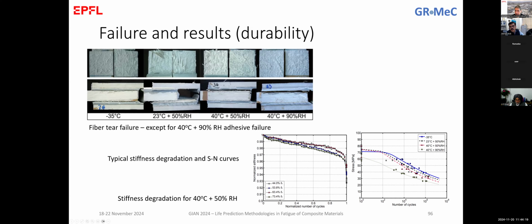So typical stiffness degradation, as before, very little stiffness degradation. You see it was only 5 to 7, 8% until failure. And of course, the expected behavior with the environmental conditions, where we have the best case scenario, the specimens tested at minus 35, then 23, then 40 without water, and then the worst case was this case where we had 40 degrees and 90% relative humidity. And I'm coming back to this discussion. This is 40 degrees, and above 40 degrees, we start having problems. And this is why this red curve is lower than the other two. And the 90 is because of the water intake that led to this failure of the interface.